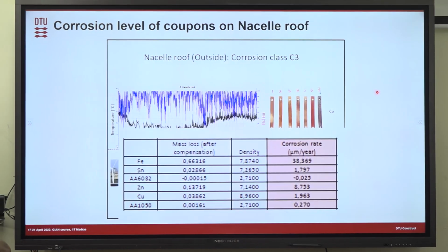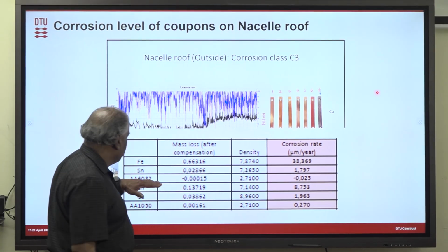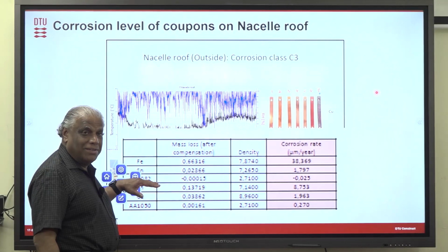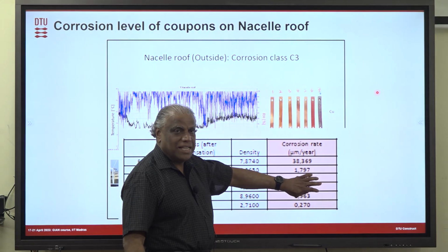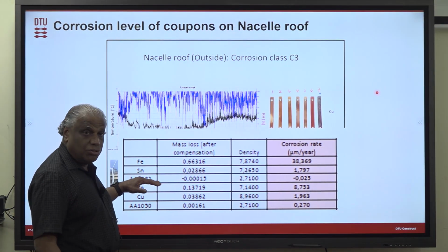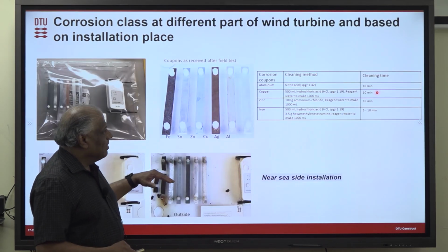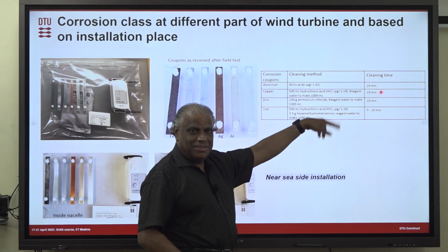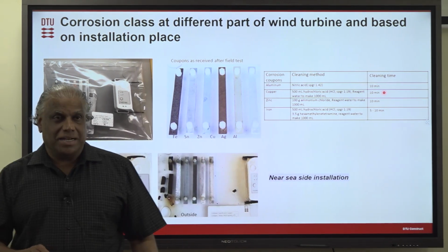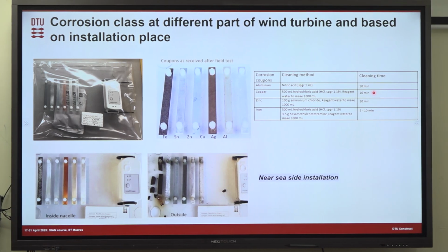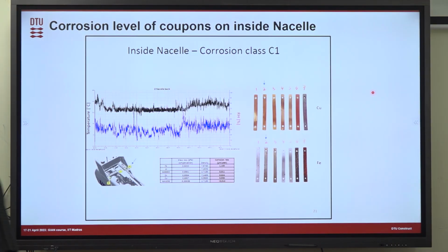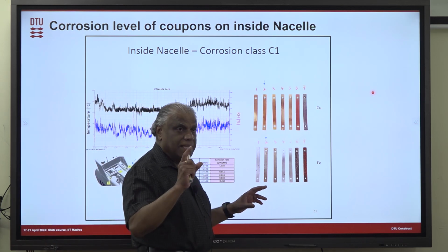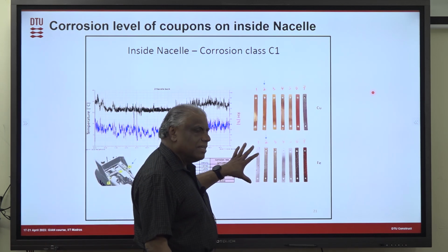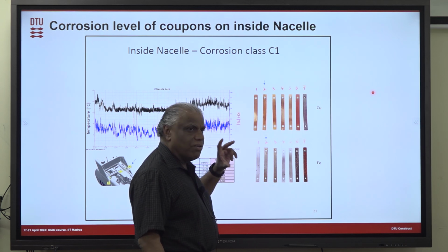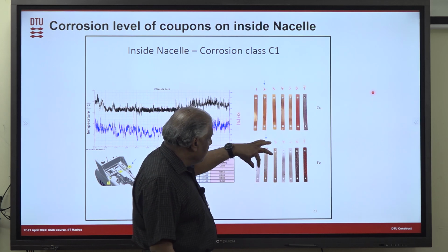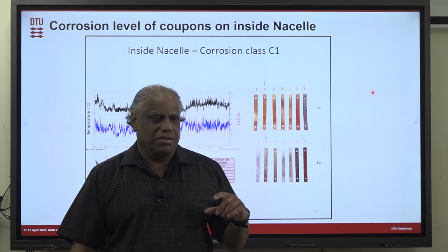Oh no, I think you need to ignore that. Basically what it shows is that the corrosion was so low here that you just ignore that value and take it as 0, because when we clean it, a little bit of material is removed from the cleaning process, and that is what you see. So it's 0 basically. I don't remember the exact size, but it's a standard ASTM ISO standard, and I think it is around 4 or 5 centimeters, and the width is close to 1 or 1.5 centimeters.